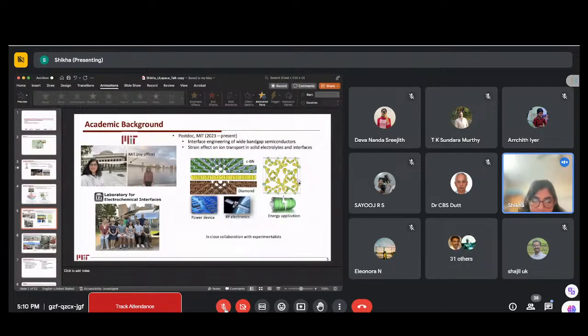So what happens at the grain boundary? When you have different facets combining at the interface, we could have different types of strain at the interface, and the local structure will change at the boundary. In electrolytes, grain boundaries usually would be there when we synthesize, and when we design computationally, our model system would be a little bit ideal compared to what we have in experiments. At the grain boundary we could have higher conductivity, and in some cases lower conductivity because of the formation of the grain boundary.